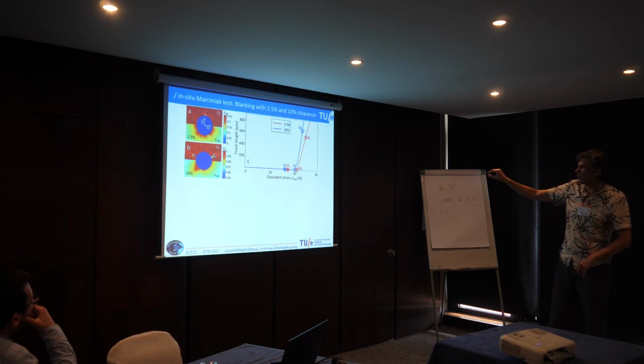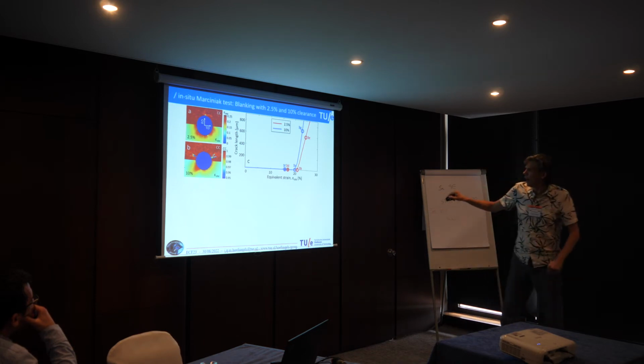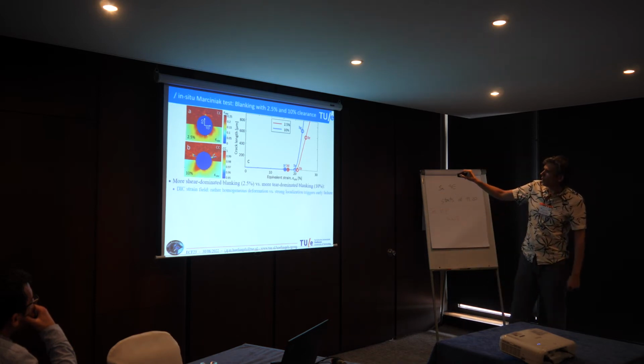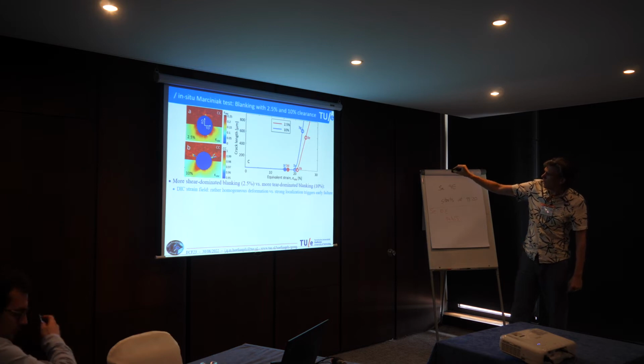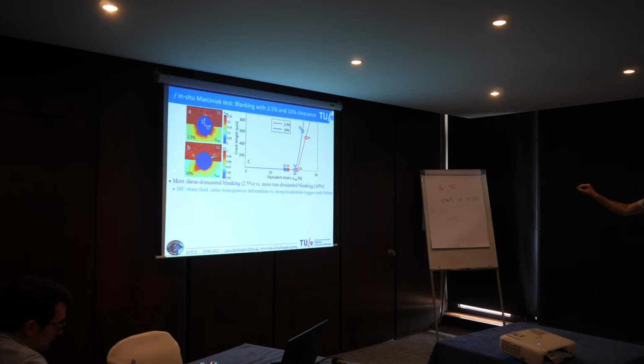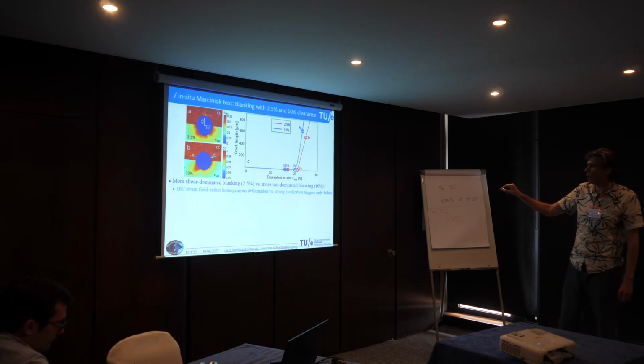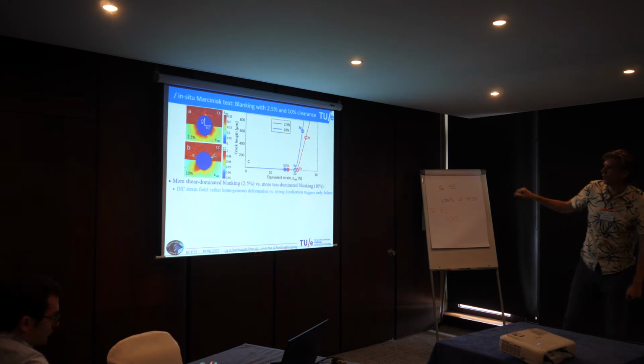So we get these strain values, and we plot them as a function of crack length, so from this point on, the crack starts initiating and it starts shooting up, and these 2 points are the points where we see the first damage occur. Okay, what can we see compared to these two clearances? We see that there's a rather homogeneous deformation in the 2.5% clearance. You can see here. First, a strong localization that triggers early failure in 10%.